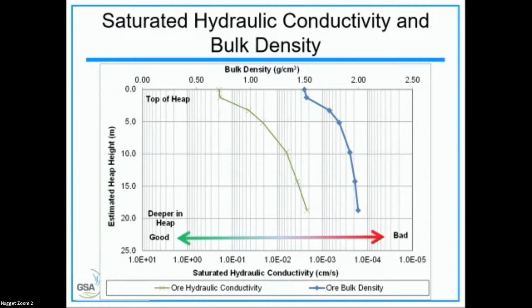What we call the safety factor, 100 times the saturated hydraulic conductivity, or the irrigation rate, is right around here. So this tells us that for this particular leach ore, they're probably going to start approaching the limit of the hydraulic capacity at about 5 meters, or let's call it 5 to 6 meters, which is probably a good lift height. But in the near surface, which is what we're interested in, the permeability is quite good.